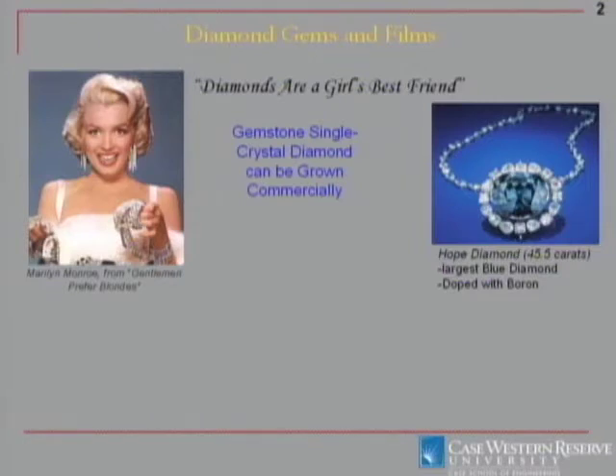actually even companies now that are growing gemstone single crystal diamonds and are competing with De Beers in the gemstone market. And so they can grow diamond actually relatively rapidly and grow it as a single crystal, so it is real diamond, it's not cubic zirconia, it's real diamond of even superior quality to what you can get out of a diamond mine, and at costs, of course, that are definitely marketable. I don't grow gemstone large diamonds, so I don't want you all coming to my lab looking for them.